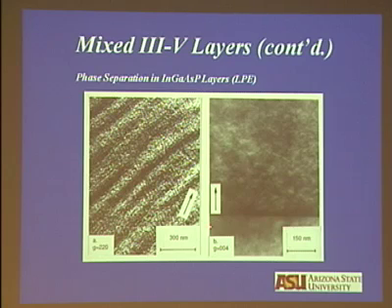And the speckle structure has a wavelength. I'll tell you how we determine the wavelength, about 8 nanometer. Very, very fine scale structure. And then you see these coarse modulations. You look at the same material with a reflection that is parallel to the growth direction. You don't see any contrast very similar to that one.